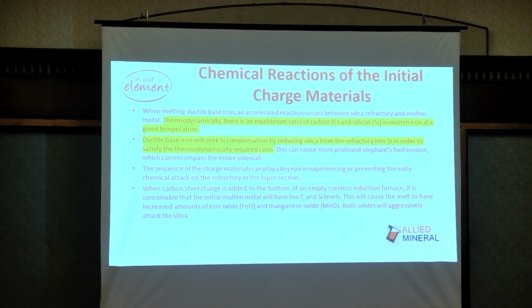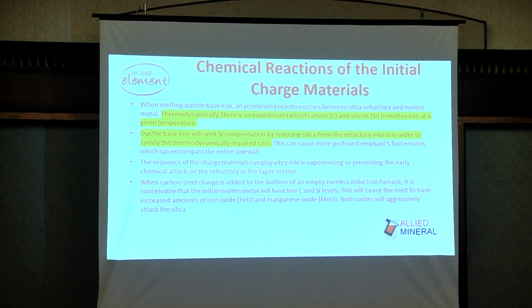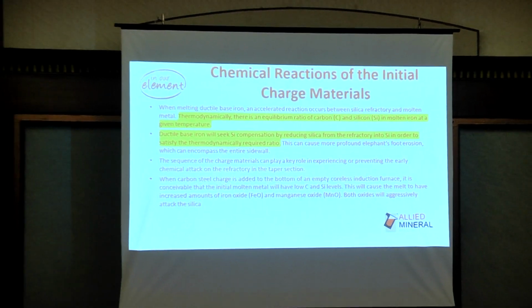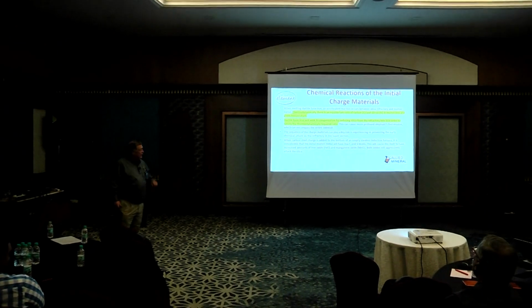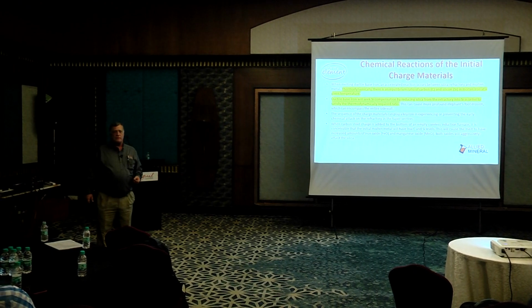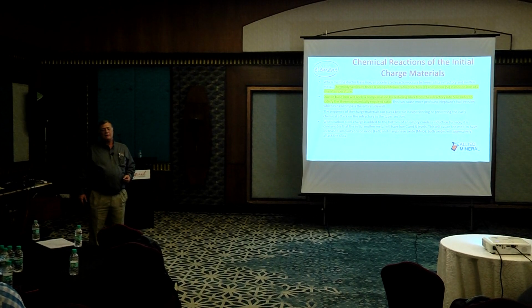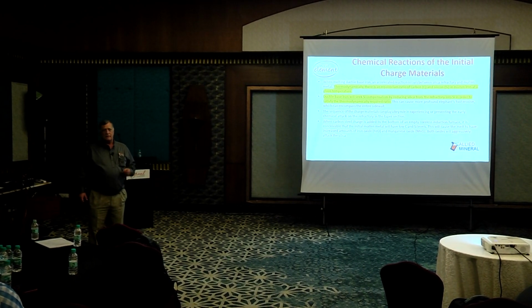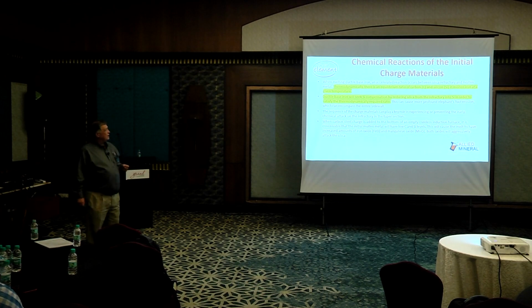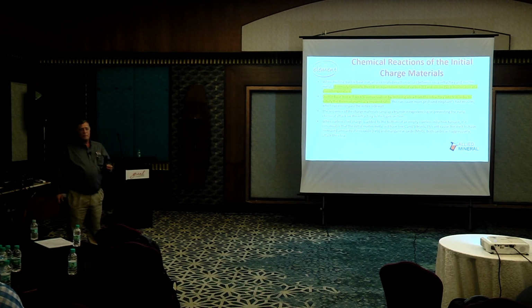Chemical reactions. Thermodynamically, there's an equilibrium carbon ratio. So if you throw off that carbon-silicon ratio, and your metal needs silicon, for example, so you're charging steel in the bottom of your furnace because you claim that it melts faster and you can save time. Well, that may be true. I don't believe it, because there's other ways that we can, by controlling the scrap size and using different types. If it's hungry for silica, silica is a very unstable material. It wants to give up its oxygen really simple.